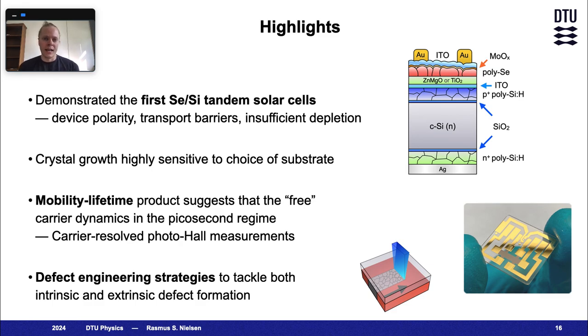And with that, I'd like to conclude my talk, highlighting just a few of the main points. We have demonstrated the first selenium-silicon tandem solar cell, and from these first iterations, we've set forth the challenges that need to be addressed on a single junction level for tandem integration to be more efficient and viable. In particular, the crystal growth is shown to be incredibly sensitive to the substrate on which it is grown. We also showed that the free carrier dynamics are more likely to be in the picosecond regime.